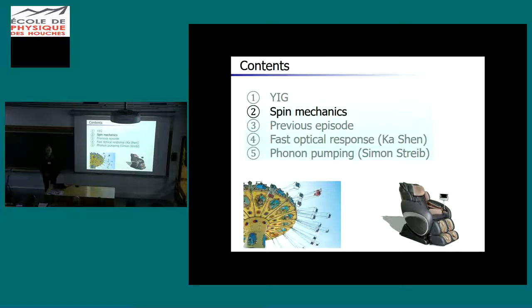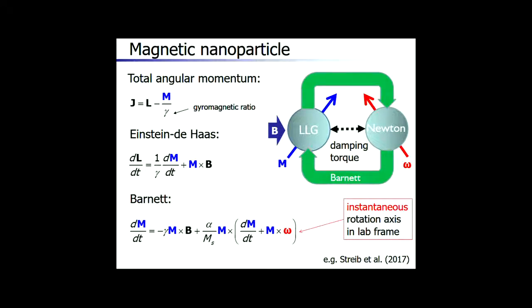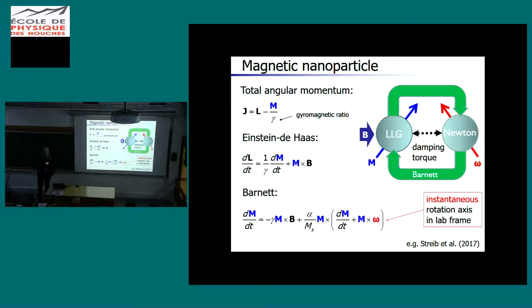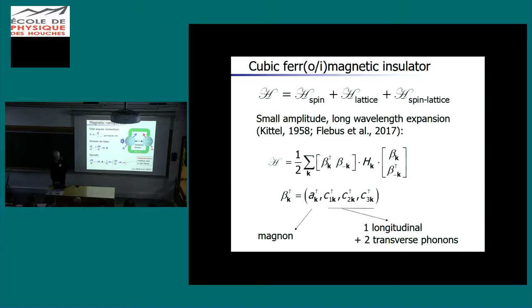Okay, let me tell you a little bit about what I think is spin mechanics. It starts basically with the Landau-Lifshitz equation and Newton's equation. We heard already about the Einstein-de Haas effect, which is basically conservation of angular momentum. We also have a reciprocal effect, which is the Barnett effect. In the absence of anisotropies, these two equations are coupled by the magnetization damping, the Gilbert damping, and the equation we have to solve for the dynamics of a magnetic nanoparticle in the classical limit would be something like that. Now these Barnett and Einstein-de Haas effects are generally important for larger frequencies. In condensed matter, we usually do not have to worry about that.